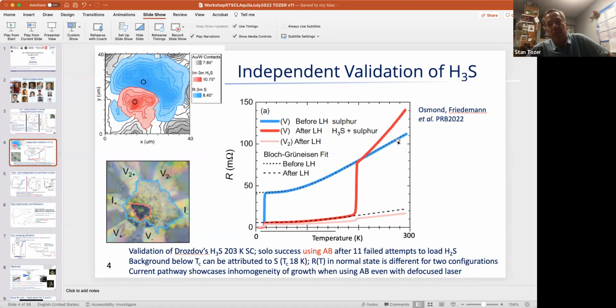And that's what happens here, right? The blue trace is just looking at the high pressure sulfur prior to laser heating. And then after laser heating, this red trace is looking across these two voltage taps, applying current across here, and they see pretty clearly this H3S material, but they also still see some sulfur here, right down at the very low TC. And then if you look across these taps, you see mostly sulfur, which is understandable, but then it does reach into and sample the superconducting material.